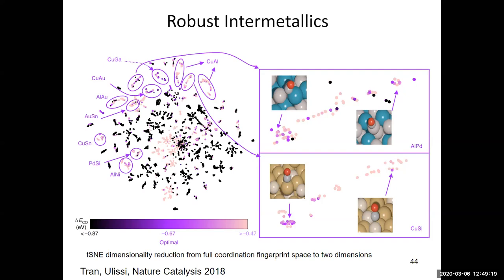And so these islands basically say, no matter how you make a copper aluminum alloy, no matter what facet you choose, all of the sites look interesting, right? There's no site on there that is going to be so strong that it poisons the surface. And so if I had to go to an experimental collaborator and say, why don't you try and make something, I would point to this one and say, start with the one where you might get lucky no matter what happens.